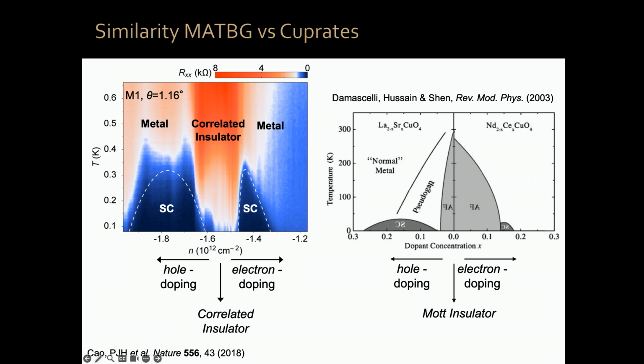Now, there are many similarities and also many differences between these two material systems and these phase diagrams. But one important difference is the fact that this is a theoretical phase diagram. In order to populate this with experimental data points, we have to grow hundreds of materials, often of different material classes, because not all materials can be grown in the same chemical composition and doping, and do hundreds of experiments cooling down and filling this phase diagram with data points.